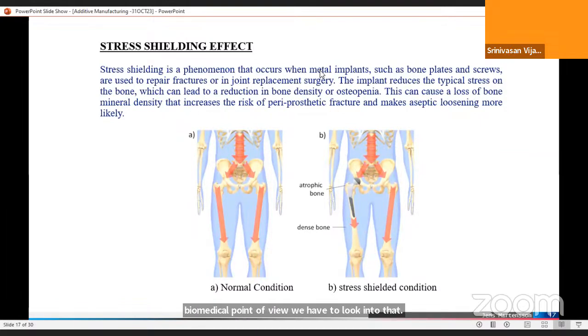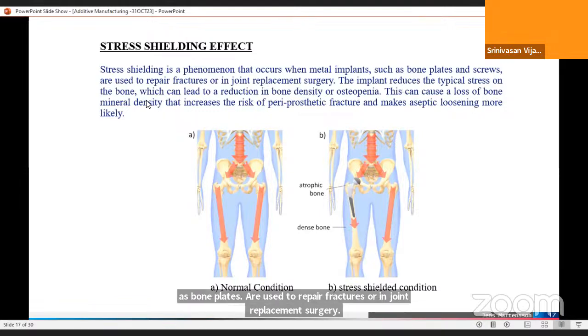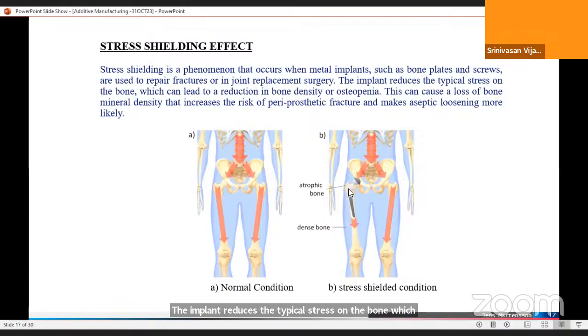It is a phenomenon that occurs when metal implants such as bone plates are used to repair fractures or in joint replacement surgery. The implant reduces the typical stress on the bone, which can lead to reduction in bone density. Actually, the bone density will be reduced if the stress is not properly distributed. This can cause loss of mineral density that increases the risk of periprosthetic fracture. Actually, the bone gets fractured. The adjacent bone will get fractured if the stress shielding effect is not taken into consideration.